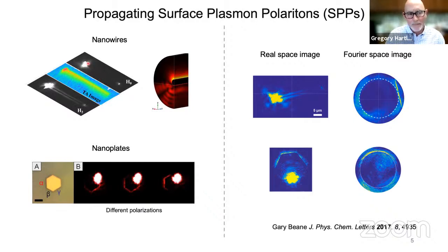So for this mode, you excite the plasmon, it moves down the wire. When it gets to the other end of the wire, there's again a break in the symmetry and a little bit of light comes out. The other type of mode has a much smaller effective index, or wave vector. So this mode that moves along the top of the surface can couple to photons in the glass. And so when you image that wire, you can see some light as the plasmon moves down the wire. This is called a leaky mode.